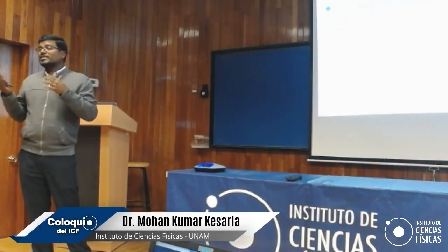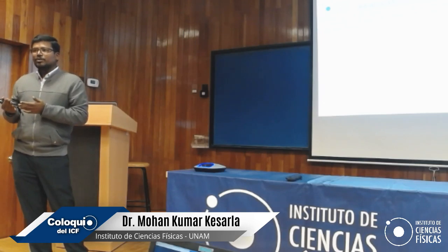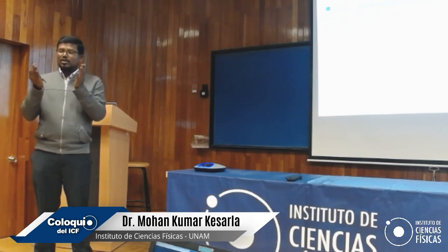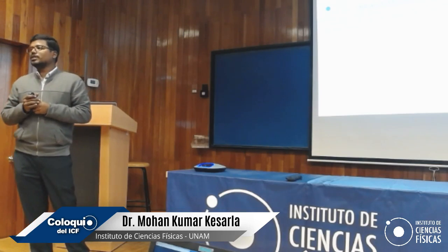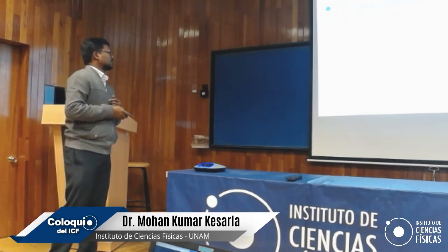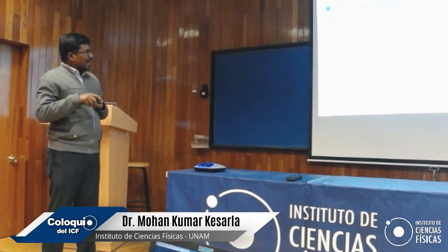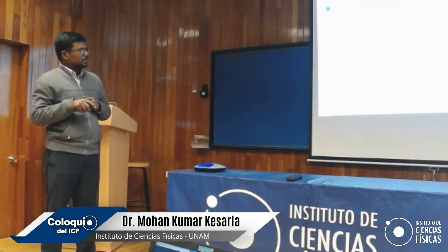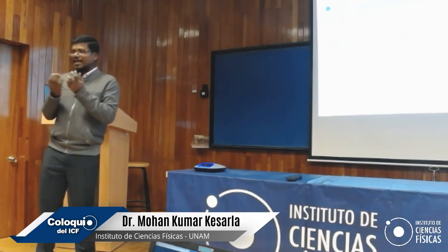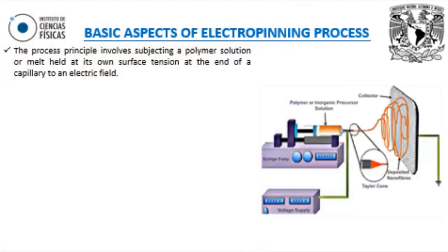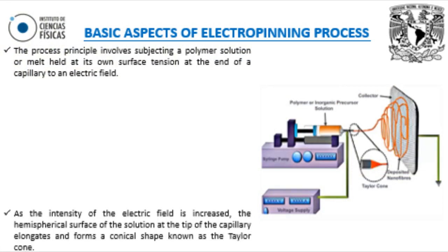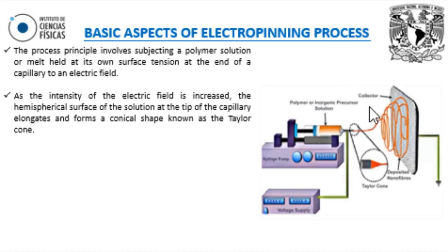Based on what solvent we use, the surface tension is going to change. Each solvent has its own surface tension, of course. If you apply an electric field, the polymer gets charged, and if you keep on increasing the electric field, it will form a hemispherical surface at the tip, and if you keep increasing it, it will elongate into a conical shape, which we call the Taylor cone.